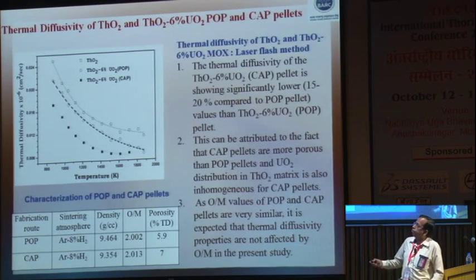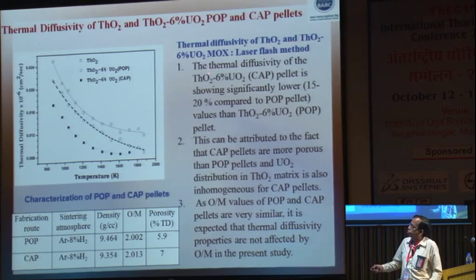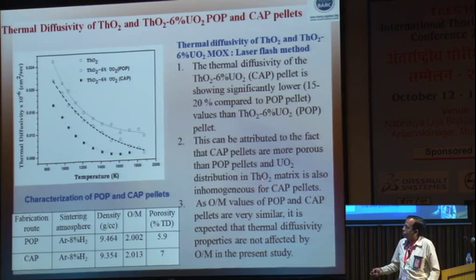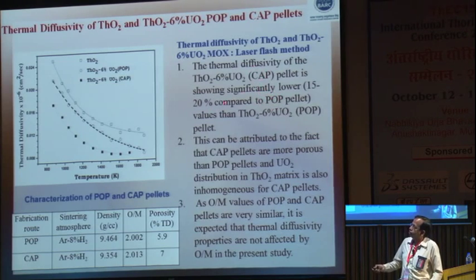That was about thorium oxide, but as I said, we have also studied thorium-uranium oxide, and here again thermal diffusivity of ThO2 and ThO2-UO2 MOX was determined by laser flash method, and these are the salient aspects of the results. There was a difference as compared to the POP and CAP process. It led to differences in thermal conductivity for obvious reasons, because there is variation in porosity as well as the density of these. The O/M ratio was not found to influence the thermal conductivity substantially. In fact, the O/M ratio itself was not very much different in all the samples that we have seen.